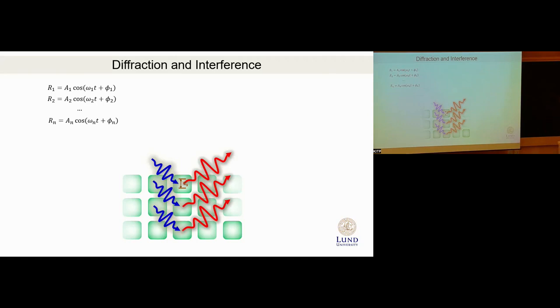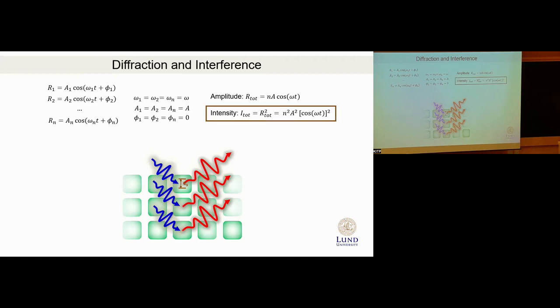Then you can write it out for n nanocrystals. If they are all the same, meaning there is no size distribution, then the frequency is identical, the amplitudes are identical, and there is no phase shift. What will happen to the collective amplitude is that you will just add them up, and the intensity, because what you measure is the intensity of the emitted electric field, you would obtain this form which scales as n squared, right? So this is basically the crux of the physics of superfluorescence.